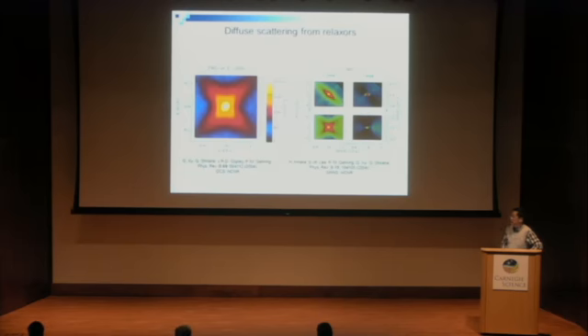Since the PNRs are atomic deviations from their perfect positions, we can use diffuse scattering to measure them, by neutron or X-ray. Here is an example of a measurement of PMN at 200 K. Around the 100 Bragg peak, we can see a butterfly-shaped diffuse intensity distribution extending along the 110 and 1-10 directions. And around other Bragg peaks, like the 110 Bragg peak, there is only one wing, but the intensity still distributes along 110 type directions.